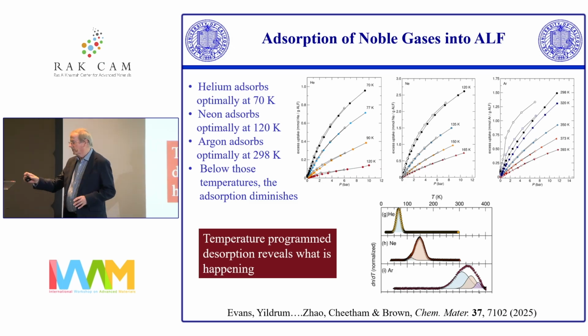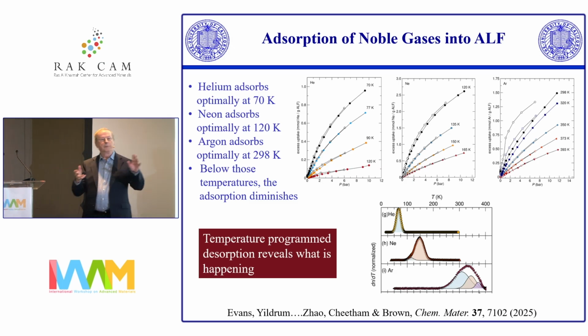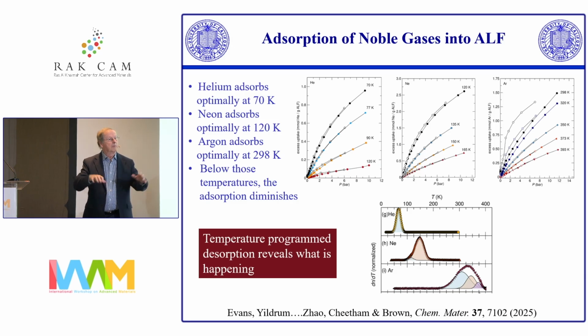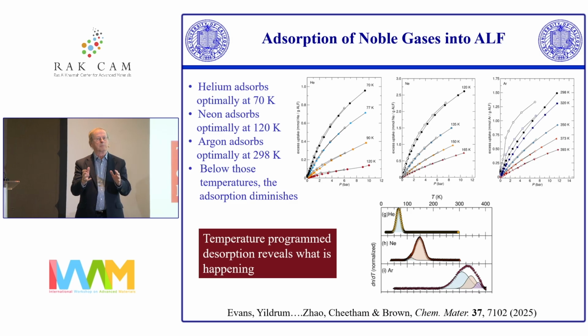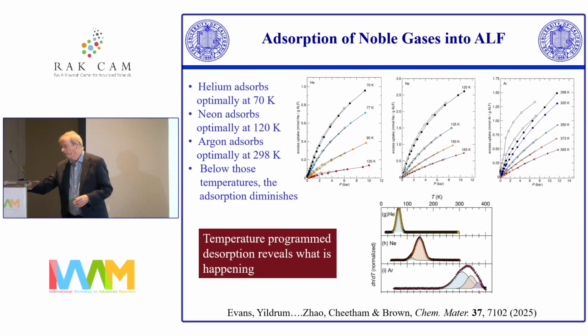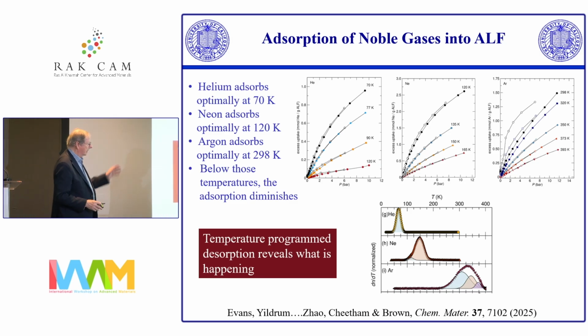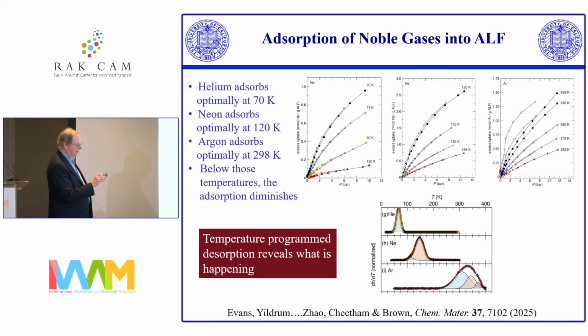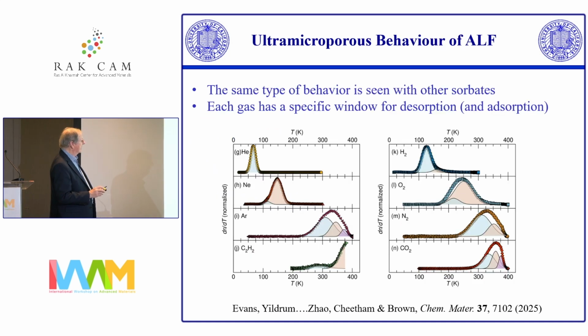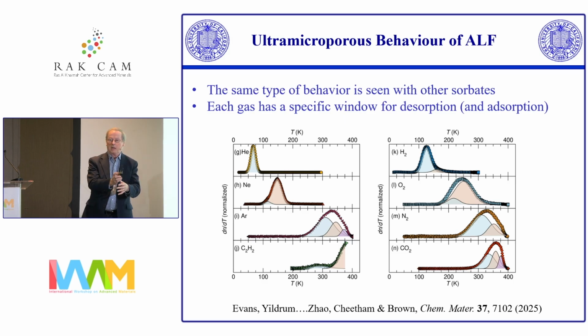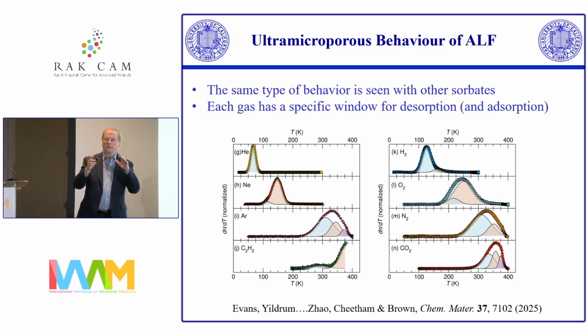So these materials, these ultra-microporous materials, of which ALF is a classical example, have critical gating temperatures, which makes them really interesting for doing adsorption properties. And so we've been looking at the reason for that with my colleagues at NIST and Hayden Evans in particular. So those things I showed you were the temperature programmed desorption. So we push the inert gas in and cool it under high pressure, cool it down, and then we follow what happens as we heat it up. That's how you get those things.